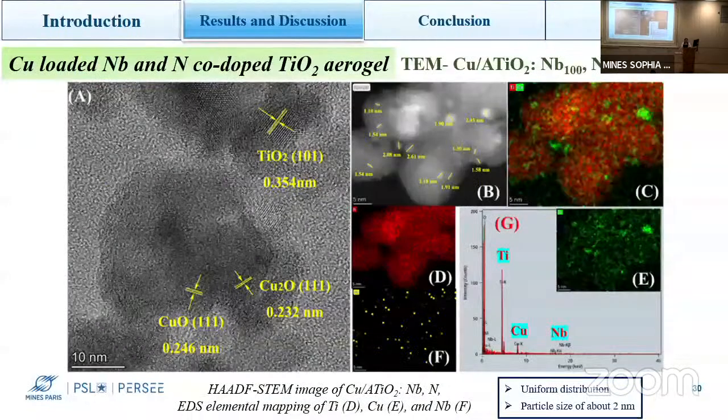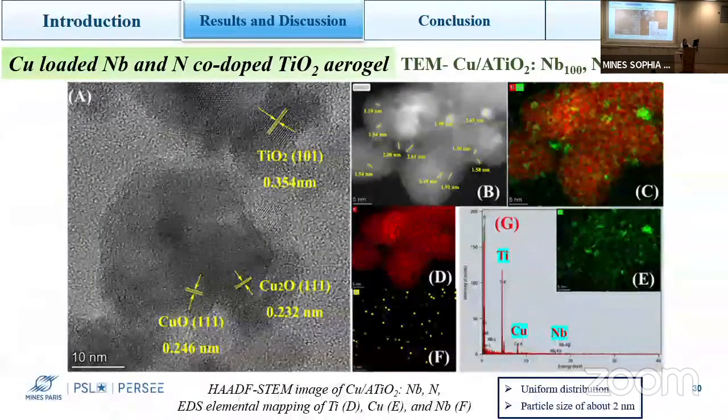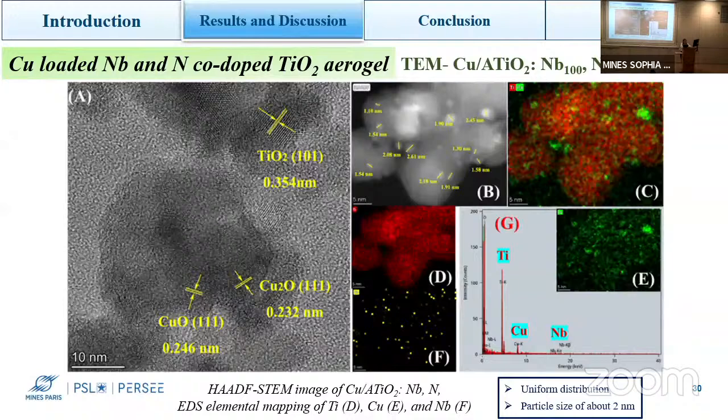Yes, for example, here it's difficult to know where is the titanium dioxide. If we look at the big one at the center of image A, it seems to be more than 20 nanometers. So now you need to see if there are some crystalline planes to be sure if it is one single particle, one core-shell particle, or an aggregate of 2 or 3 different particles.